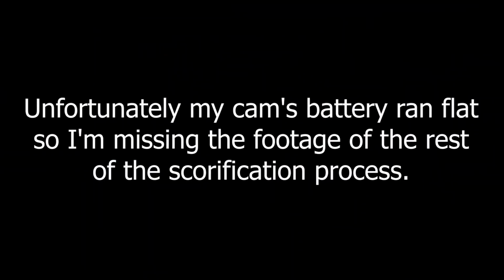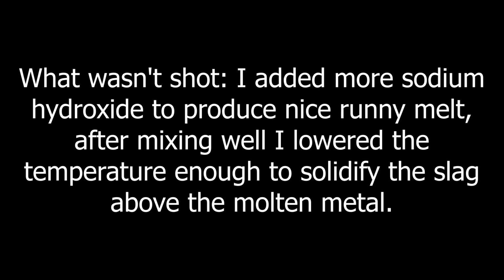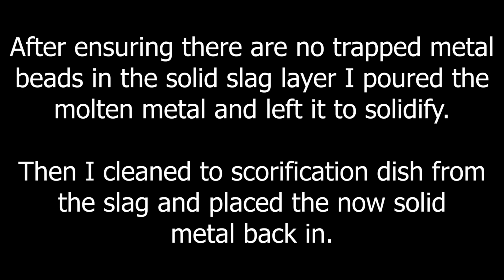Unfortunately, my cam's battery ran flat, so I'm missing the footage of the rest of the scorification process. What wasn't shot? I added more sodium hydroxide to produce nice runny melt. After mixing well, I lowered the temperature enough to solidify the slag above the molten metal. After ensuring there are no trapped metal beads in the solid slag layer, I poured the molten metal and left it to solidify. Then I cleaned the scorification dish from the slag and placed the now solid metal back in.